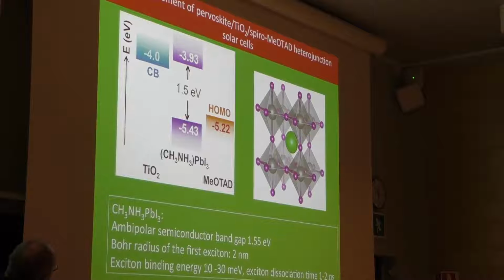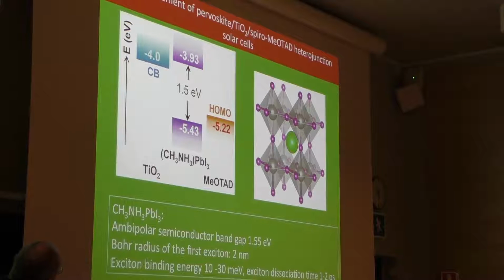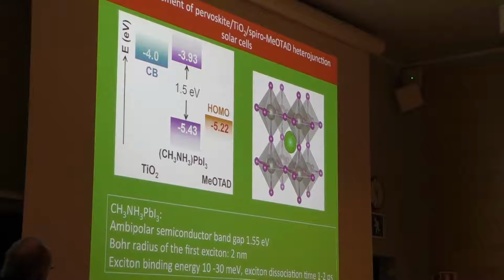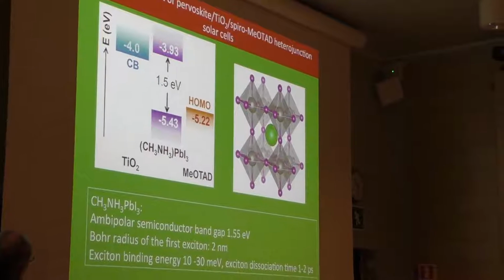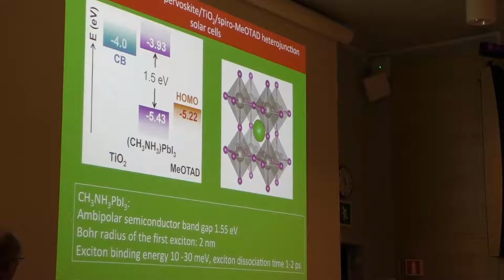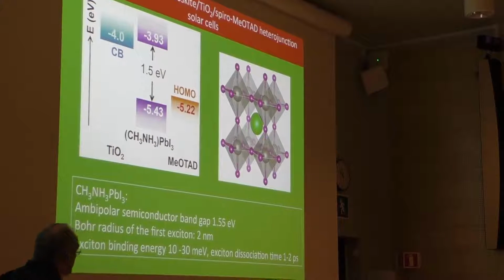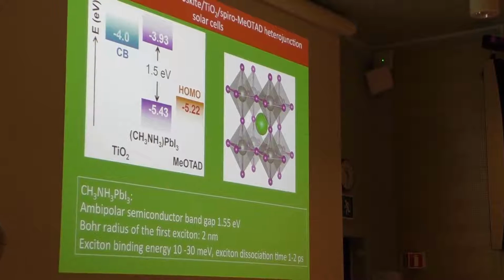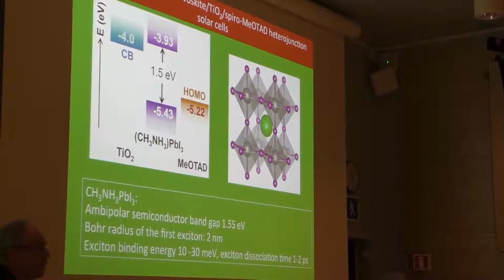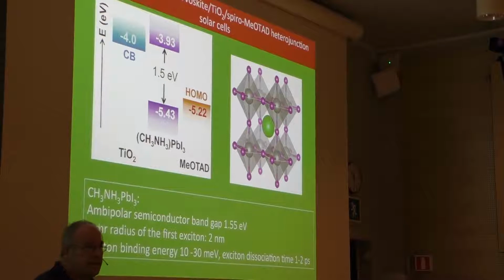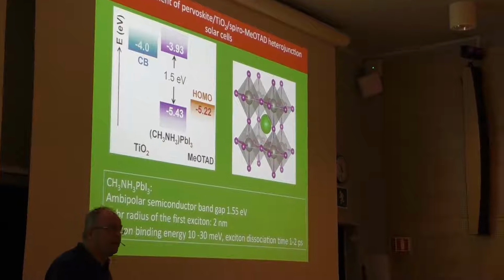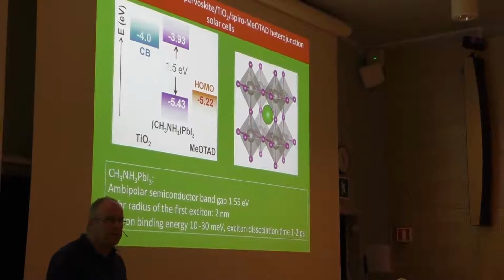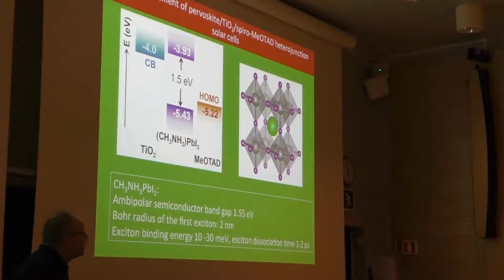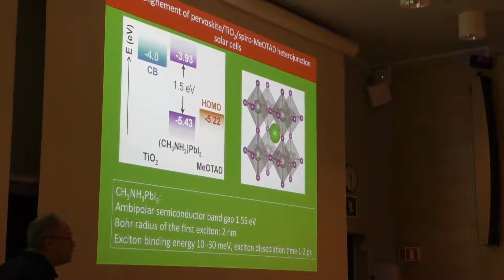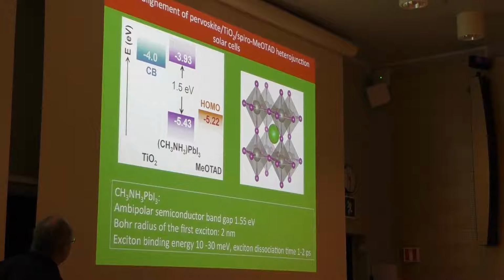So the starting point was to use this perovskite, and then you had TiO2 and then Spiro as the hole conductor. So very much like a dye cell, you inject electrons into TiO2 and holes into the Spiro. It has low exciton binding energy, so you really separate the electron-hole pair very quickly and efficiently. So it's a very ideal semiconductor, and you can prepare it from solution. That's the real interesting part if you compare to silicon and gallium arsenide.